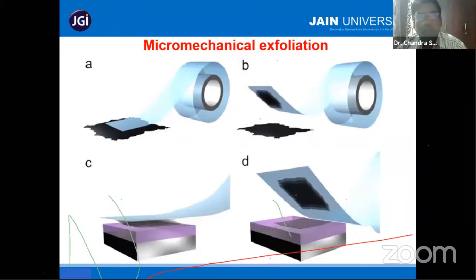So this is the micromechanical exfoliation method. This was the method that Novoselov and Andre Geim first followed to achieve single layer graphene. For that, they won the Nobel Prize. What they did is they took HOPG, a carbon source, a carbon substrate. HOPG is highly oriented pyrolytic graphite. From this graphite, you have to take one Scotch tape. Scotch tape is easily available everywhere.